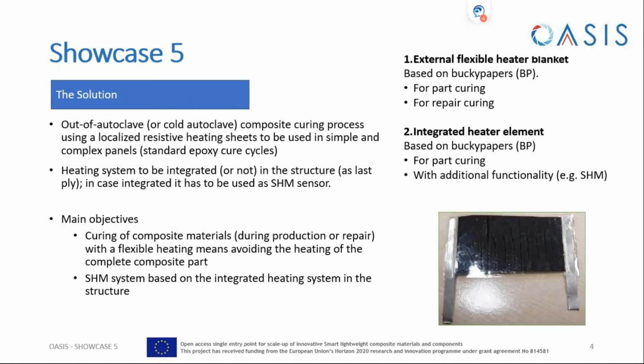So what we are asking of Showcase 5 and the OASIS project is an out-of-autoclave composite curing process using a resistive heating sheet that is flexible enough to be adapted to simple and also complex panels, and fulfilling the standard epoxy cure material cycles. This heating system can be integrated or not in our structure, but in case it is integrated, we have to find an application, for instance structural health monitoring.